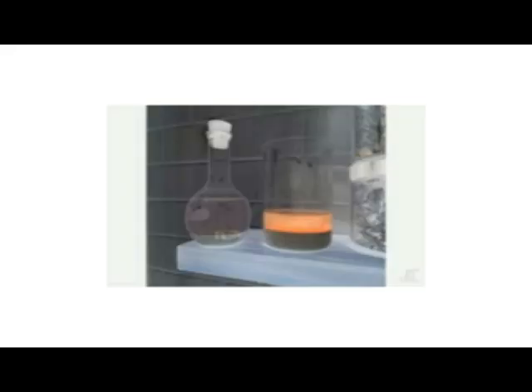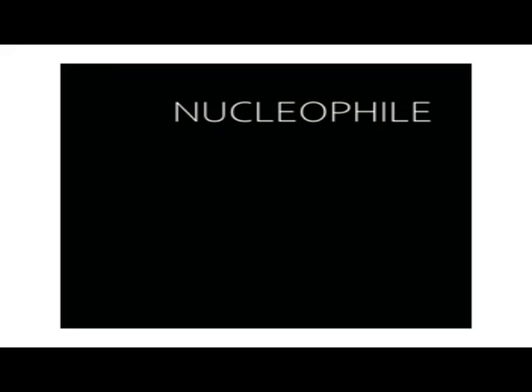Some procedures use a large molar excess of sodium bisulfate to improve yield. So I'm trying that here using 43 grams of sodium nitrate and 150 grams of sodium bisulfate, which is a little over 2 molar equivalents to the sodium nitrate. Hopefully this will drive the reaction forward and improve yield.